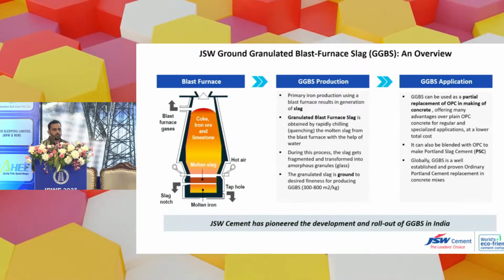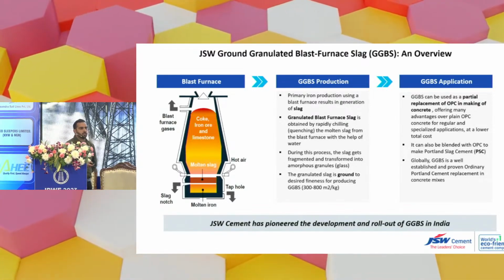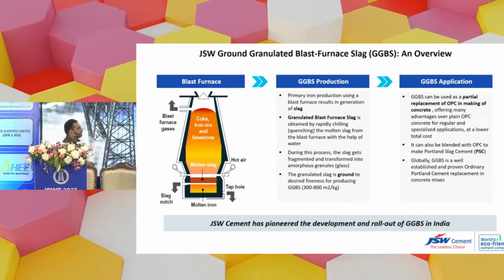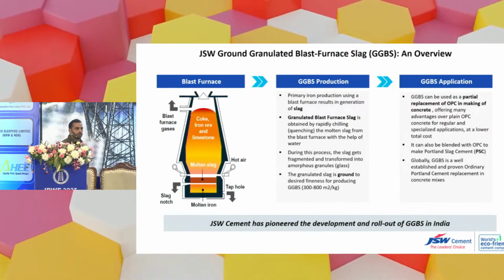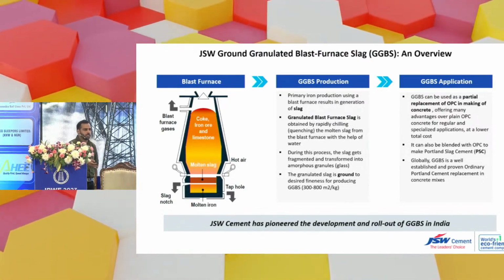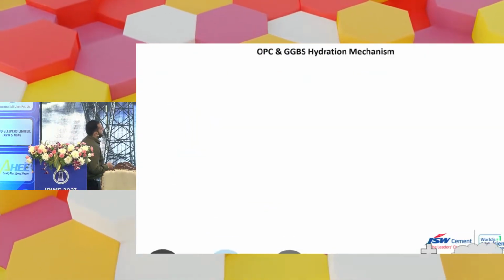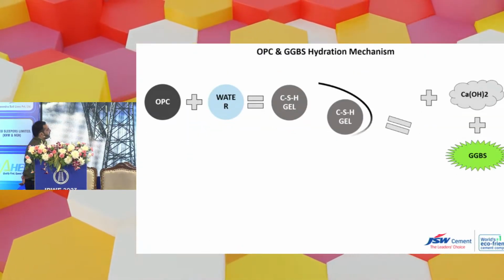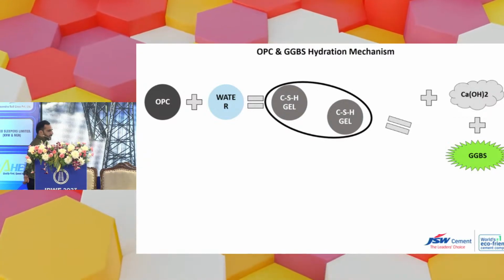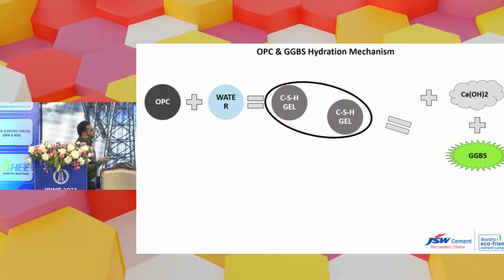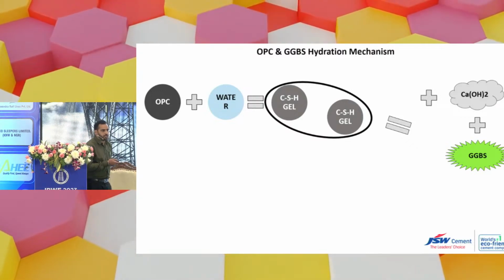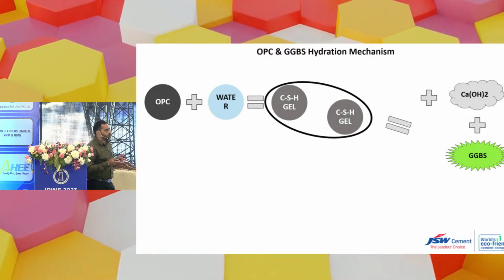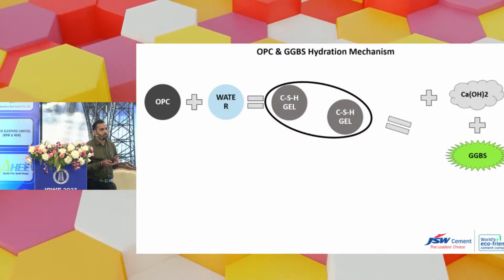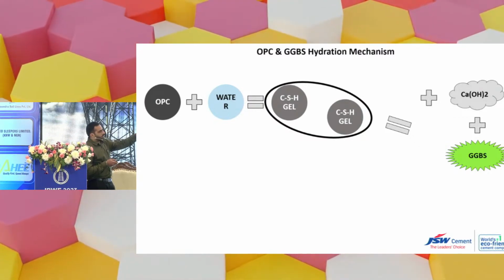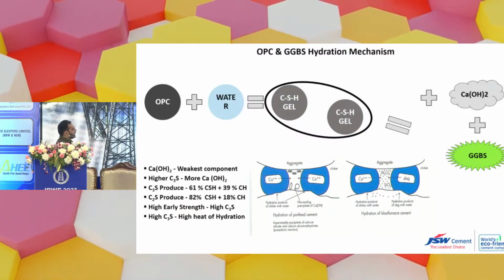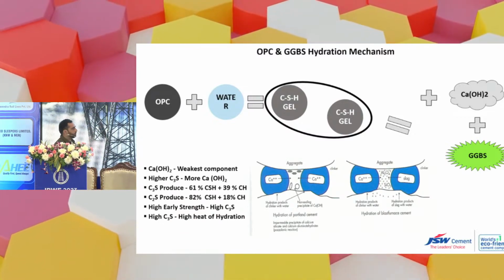GGBS is basically a partial replacement of OPC material and other cement supplementary materials. As per the Indian standard, we can replace OPC cement anywhere between 25 to 65% as per the various applications of the concrete. This is how GGBS works. When OPC reacts with water, CSH gel gets generated. In addition to the CSH gel, there is also calcium hydroxide, which has a nature of expansion. You see a lot of cracks in mass concrete structures. With Ca(OH)2, our GGBS reacts and makes further CSH gel, which helps long-term strength.